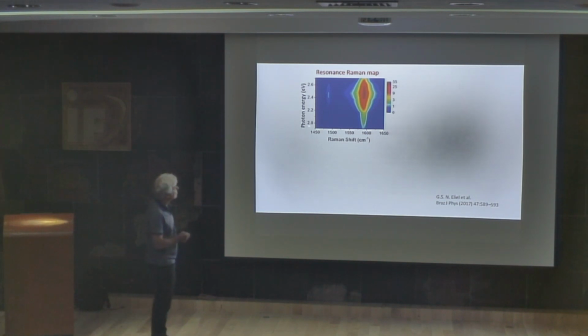Here in the horizontal scale is the Raman shift, and in the vertical scale is the energy of the photon. I'm using here, for example, this is red, this is blue. Then I'm making many different spectra, from the red to the blue laser. And the color scale is the intensity of the peak. Then there is one peak here and another peak here.